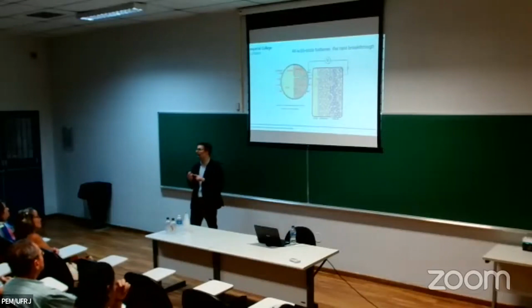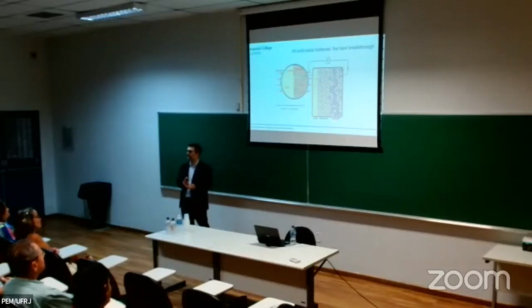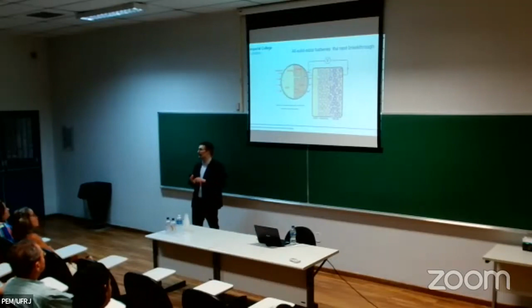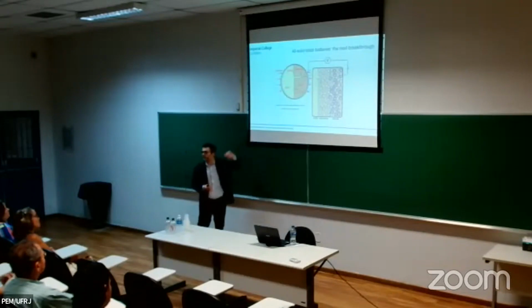So the idea would be to improve safety by having a solid electrolyte, so replace the liquid electrolyte by a solid electrolyte. And also you can increase capacity by an order of magnitude, because then you can use lithium metal as an anode, which becomes stable with the solid electrolytes. It's not stable with those aqueous electrolytes. So you can increase capacity by an order of magnitude, and you can remove all the safety concerns related to batteries. So it's really the next big breakthrough in battery technology.